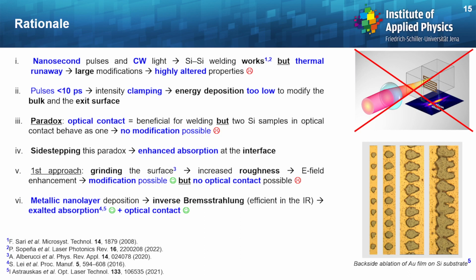So as a method we propose, we want to deposit some metallic nanolayer at the interface between the two silicon samples, because then we have high absorption because of the free electrons of the metal through inverse Bremsstrahlung, meaning that the absorption would be exalted, and at the same time we can maintain the surface quality, so the optical contact should be theoretically achievable in that case.